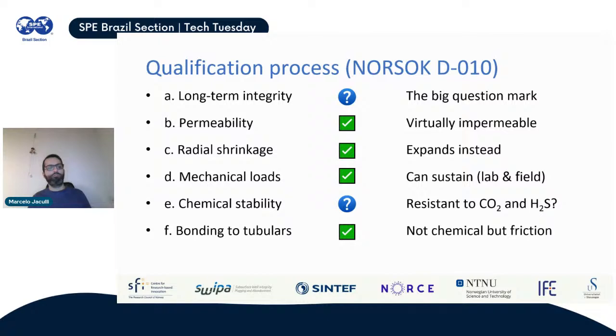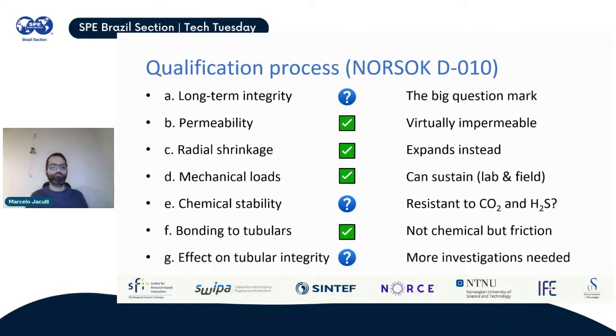Bonding to tubulars. Any alternative material must be able to bond to tubulars. But as I explained in the beginning, there is no chemical bond between bismuth and the steel. Because there are two metals, they are not interacting with each other. We're not welding them together. So the only type of bonding that we have is mechanical bonding. It's an adherence between the plug and the pipe inner wall. So we have friction holding them together, and we can say that the plug is bonding to the tubular due to friction.